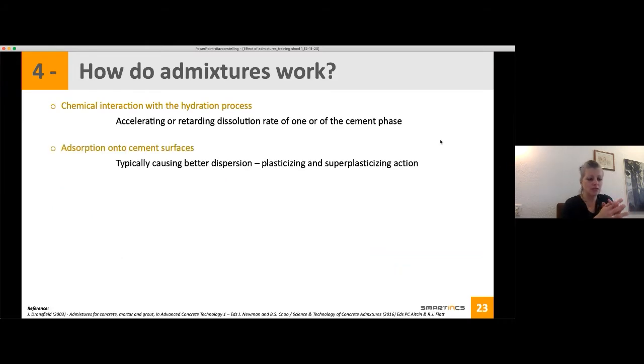But another way is, you have your cement particles, and you have some charges over there, and you can have your admixtures adsorb on the surface of your cement particles, which means that if you have two particles and you have admixture around them, then you will create some space between these particles, so you will have better dispersion. And this is typically what we get of the mechanisms with plasticizing and superplasticizing admixture.